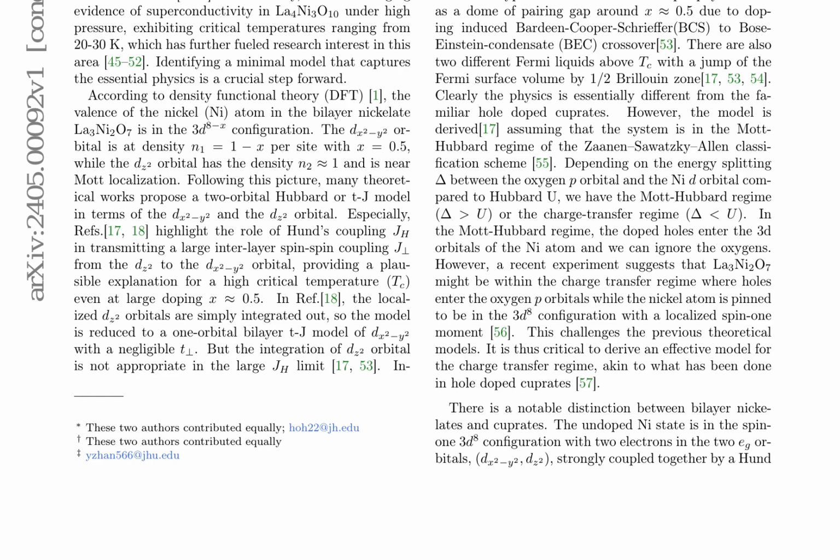As r approaches infinity, the entanglement entropy approaches zero, indicating that the Zhang-Rice spin 1/2 state becomes a tensor product of the singlet formed by the d1 and p1 orbitals, and the spin 1/2 of the d2 orbital. These calculations provide a detailed analysis of the effective Hamiltonian components and bipartite entanglement entropy for the Zhang-Rice spin 1/2 state, vital for understanding its stability and properties in the context of high-temperature superconductors.